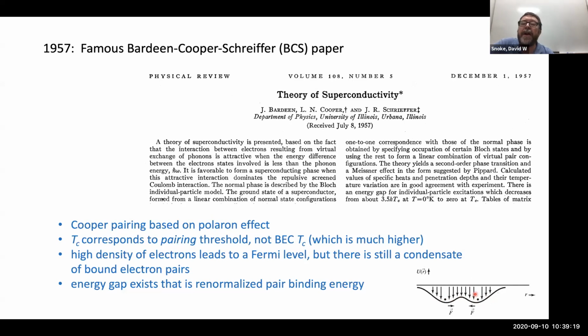It turns out in actual BCS superconductors, the TC that we see is the TC for becoming pairs, so going from free electrons that are unpaired to pairing up. And so the TC is related to the binding energy of the pairs. It's not the BEC critical temperature, which is actually much higher. And in the context of high TC, there's been debate about whether it could be the other way around. These are two different TCs.